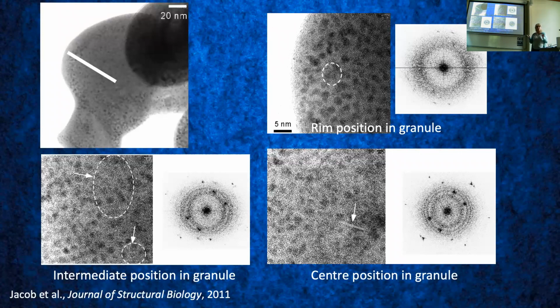It was unavoidable, but we documented every step, and you can actually take precautions to be sure if you're creating artifacts or not. And even if we created an artifact, that just means it was all amorphous before. I'm just pointing this out because in the transmission electron microscopy literature, there are actually a lot of artifacts. And it's one of the main jobs of publishing in that area to have a foolproof protocol to check and recheck yourself if you're going down a rabbit hole and looking at artifacts.